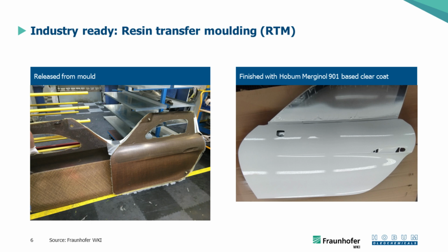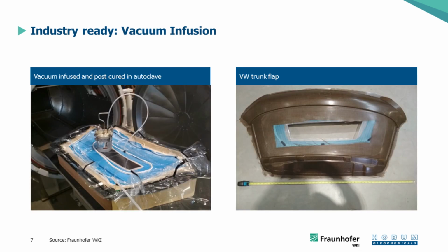So the entire making of this door led to a pretty good content of renewable materials. We reached at the design freeze, that was already some time ago, roughly 70% bio-based material. Big part, of course, comes from the flax fiber.